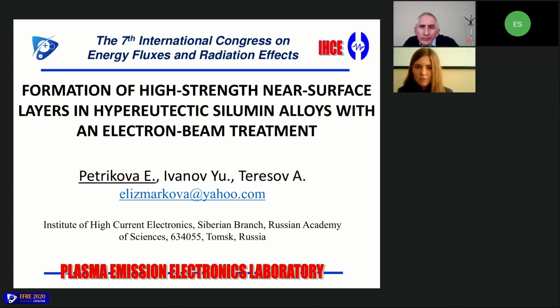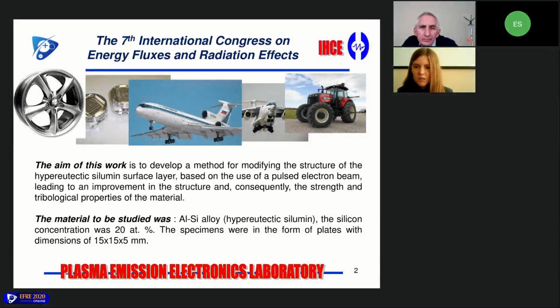The microstructure of these casting alloys contains dendrites of alpha solid solution, primary silicon crystals, and many intermetallic phases. The size, morphology, and distribution of microstructural features govern the mechanical properties of these alloys. And it's well known that a refined microstructure results in improved tensile properties. The refinement of microstructure can be achieved through high cooling rate or chemical modification.